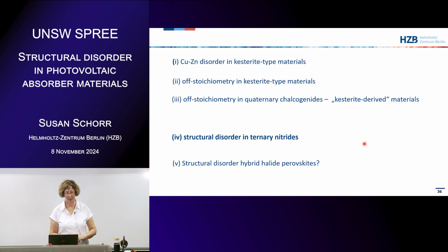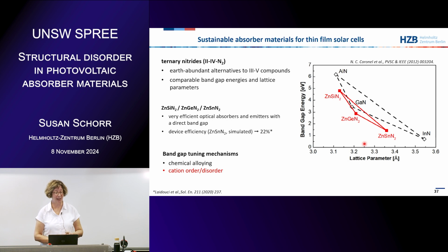Now going away from the chalcogenides, I'll show you a little bit about ternary nitrides we studied. Why ternary nitrides? We look for sustainable absorber materials, and the ternary nitrides are said to be potential earth-abundant alternatives for III-V compound semiconductors, like aluminum nitride, gallium nitride, indium nitride, you know all that. Ternary nitrides like zinc silicon nitride or zinc germanium nitride, which is shown here, or zinc tin nitride, this is the band gap, are possible materials also for solar cells. There is a simulated device efficiency reported for zinc tin nitride of about 22%.